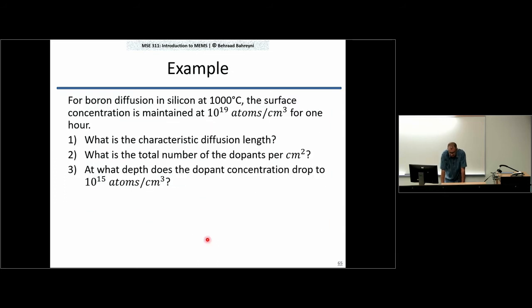So let's look at an example here. We are doing a boron diffusion at 1000 degrees Celsius, and the surface concentration is maintained at 10 to the 19. So let me just write down these numbers here. And we do this for 1 hour. The question is 3 parts. What is the characteristic diffusion length? Second part, what is the total number of dopants per centimeter squared?